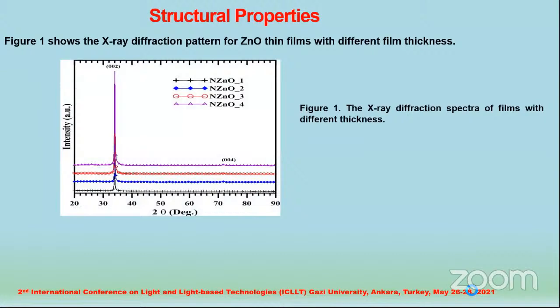Structural properties. The crystalline quality and orientation of the nitrogen zinc oxide thin films have been investigated by means of X-ray diffraction (XRD). Figure 1 shows the X-ray diffraction pattern for zinc oxide thin films with different film thickness: NZNO1 250 nanometers, NZNO2 350 nanometers, NZNO3 450 nanometers, NZNO4 550 nanometers. Thin films were deposited on glass substrate.